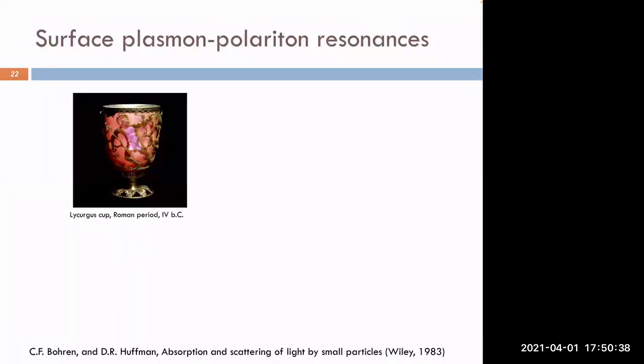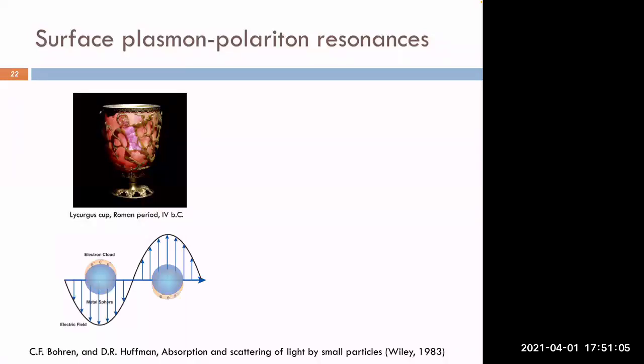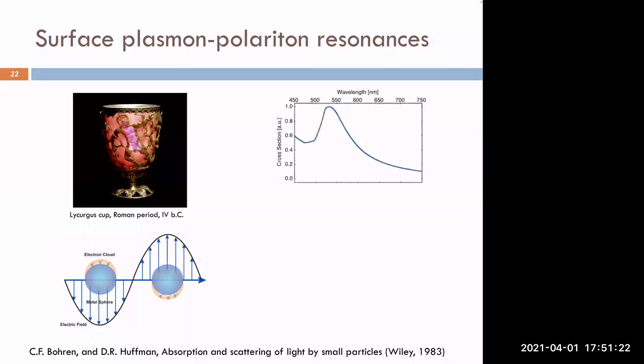Okay, so now I don't have so much time left because I promised to stay within 45 minutes. So let me accelerate a little bit here. So far we talked about the diamond system and about the electronic properties. Now I want to talk about how you can improve the optical properties using a photonics approach. One approach that we use is based on surface plasmon-polariton resonances. You know that metal nanoparticles have unique optical properties in the sense that they have a surface plasmon resonance that is due to the coherent excitation of the electron cloud in the metal, which gives rise to a broad resonance peak in the visible spectral range.